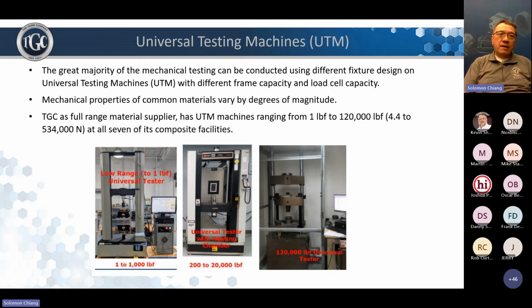At our company, we have a universal tester as low as 1 to 1,000 pound maximum. Those are the ones we use for flexible materials, some thermoplastic, and paper. Most composite material can be tested with a 20,000 pound, or 20 kip, universal tester. But when you get into heavy wall stuff, 1 inch wall and above, obviously you need more tonnage, like a 120,000 pound or 60-ton machine, in order to perform the testing to failure.